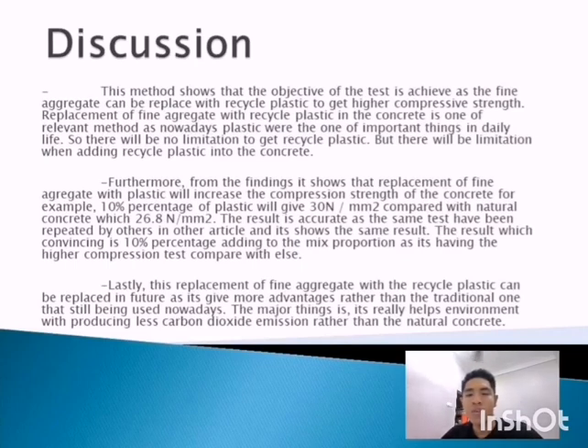Replacement of fine aggregate with recycled plastic in the concrete is a relevant method, as nowadays plastic is one of the important things in daily life. So there will be no limitation in getting recycled plastic, but there will be a limitation when adding recycled plastic into the concrete. Furthermore, the finding shows that replacement of fine aggregate with plastic will increase the compressive strength of the concrete. For example, 10% of plastic will give 30 Newton per millimeter squared compared with natural concrete, which is 26.8 Newton per millimeter squared.